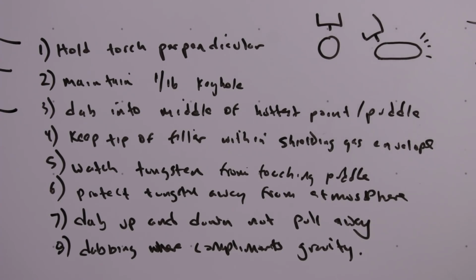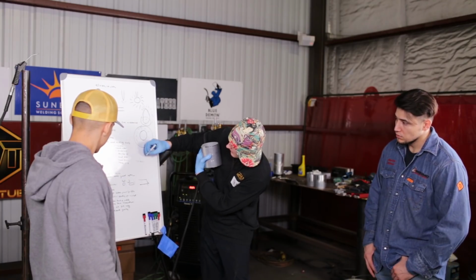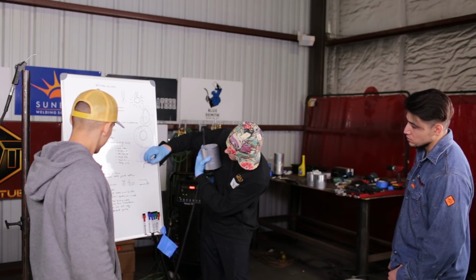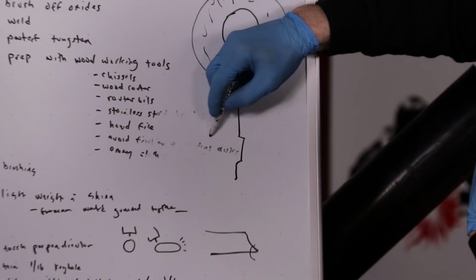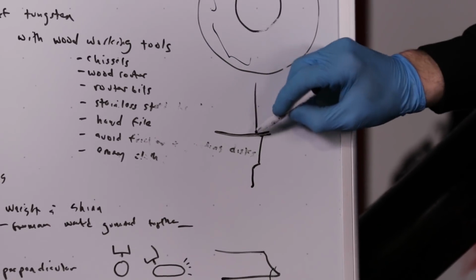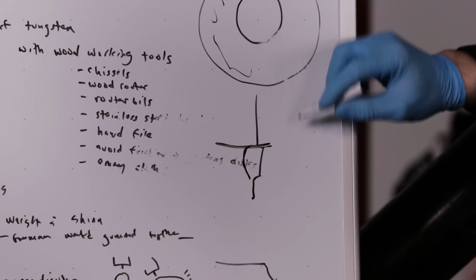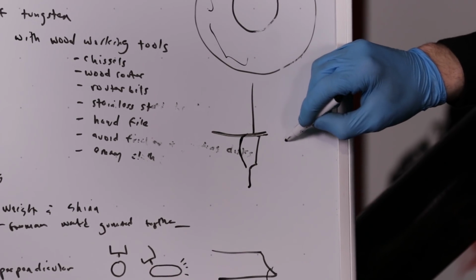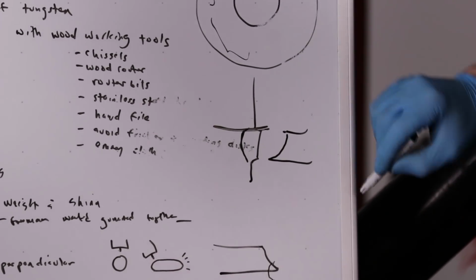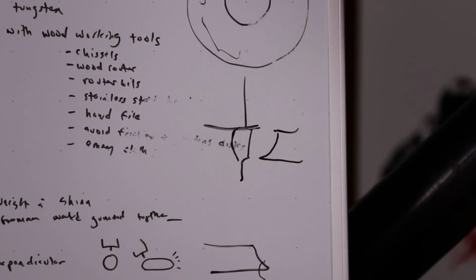So depending on the position of the pipe, I have to dab differently. For example, if it's a 2G, I have to always add fill metal to the uppermost portion of the pipe, and gravity pulls it down. Exactly. And even on a fill pass, otherwise it ends up as a bell shape. So if this is my weld here, and I add fill metal at the top, gravity will pull it down uniform. Otherwise, if I add fill metal to the bottom, it comes out like a bell. Yes, exactly. So that takes care of dabbing into the middle of the hottest point.